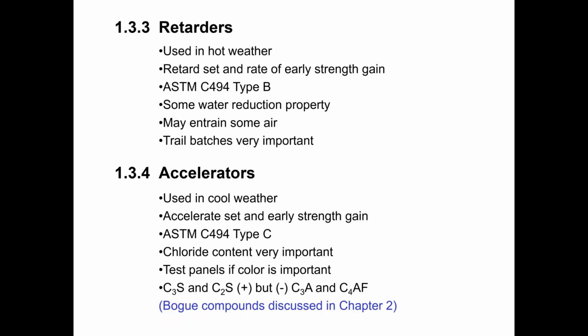All right, the opposite of retarders are accelerators. Accelerators are typically used in cooler weather to help speed up the initial set and early strength gain of the concrete. So using an accelerator will help us to get the strength that we need for stripping so that we can turn the form over more frequently and have a more economical operation. So the way these work is they speed up the initial setting and strength gain of the oxides within the cement that contribute to early strength gain.